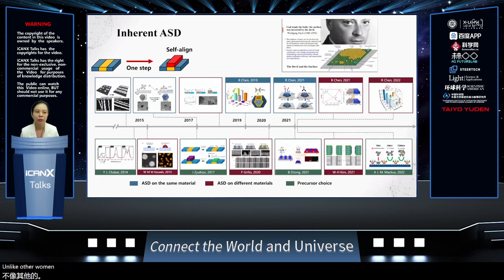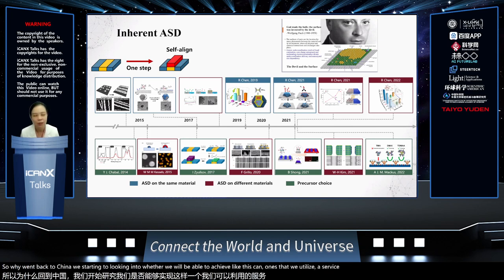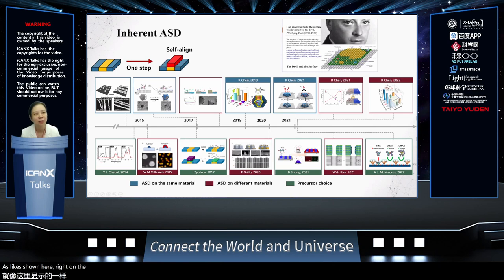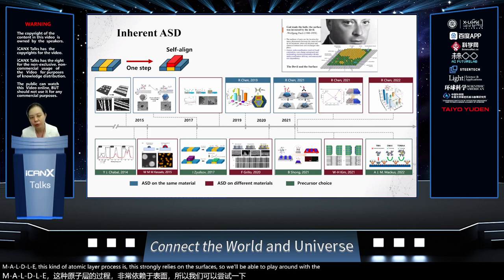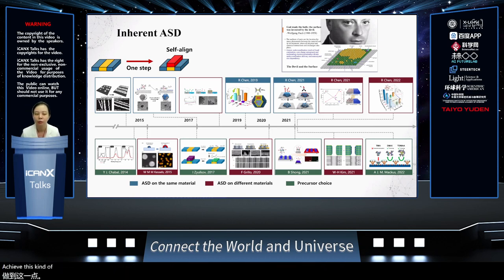But we researchers from universities are looking into the next step. So when I went back to China, we started looking into whether we would be able to achieve this kind of one step. We utilize the surfaces, as shown here on the right. The Nobel laureate Pauli mentioned that God made the bulk and the surface was invented by the devil. Definitely, the surface is a lot more complicated than we can really control. But the good thing is ALD and ALE, this kind of atomic layer processes, strongly rely on the surfaces. So we will be able to play around with the surface to achieve this kind of selective process.